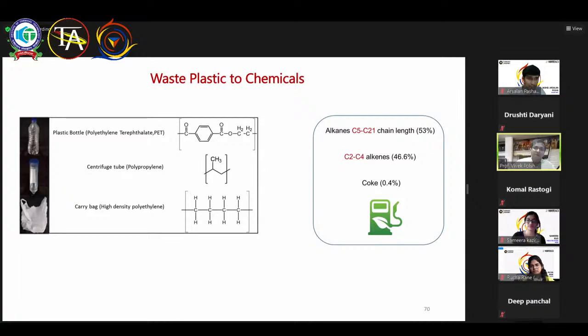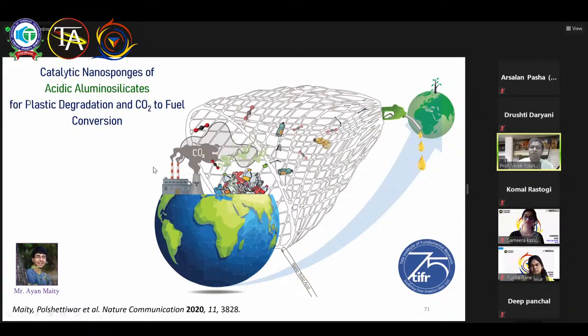Economically, it's not sustainable. So somehow I need to reduce the temperature required to degrade these plastics back to the chemicals. And if that happens by a catalytic process, then this could be feasible. In order to reduce the degradation temperature of the plastic, you need to use some sort of acid catalyzed degradation, acid catalyzed C-C bond breaking, and solid acids, the solid materials having acidic properties, are known to be the best. But the materials reported in the literature were strongly acidic, but the pore size of these solids is so small that the plastic cannot diffuse in, and therefore they cannot degrade.